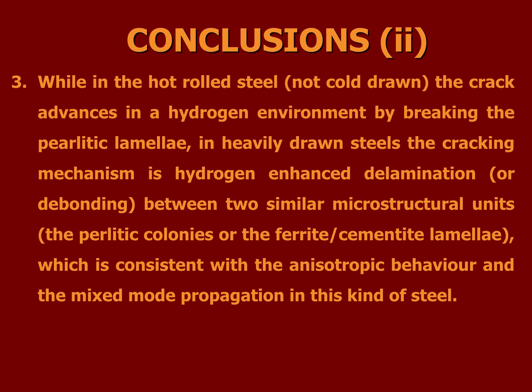While in the hot rolled steel, not cold drawn, the crack advances in a hydrogen environment by breaking the pearlitic lamella, in heavily drawn steels, the cracking mechanism is hydrogen-enhanced delamination or decohesion of the bonding between two similar microstructural units, the pearlitic colonies or the ferrite-cementite lamella, which is consistent with the anisotropic behavior and the mixed mode propagation in this kind of steel. It is longitudinal splitting, or delamination, or decohesion.